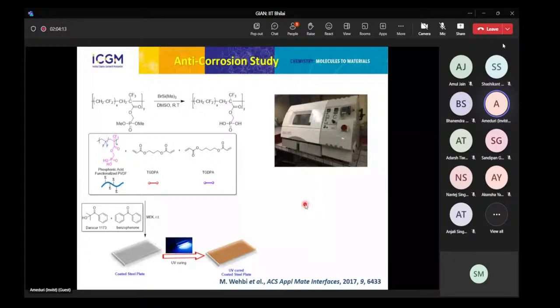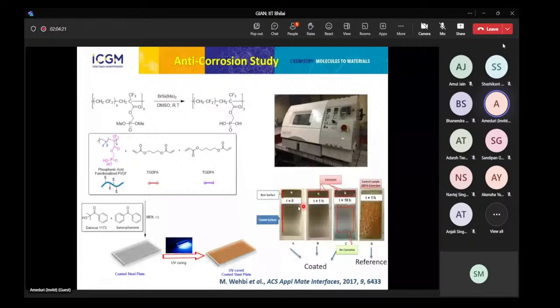So this steel was not coated, and after 1 hour it was corroded, so the rust was here. And as you can see here, the different plates coated with this formulation were very stable and could ensure a good anti-corrosion property. So this was because of the presence of phosphorus, and because, of course, the presence of PVDF, meaning that the phosphonic acid enabled to have a good adhesion on the steel, while the PVDF a good protection against the moisture.